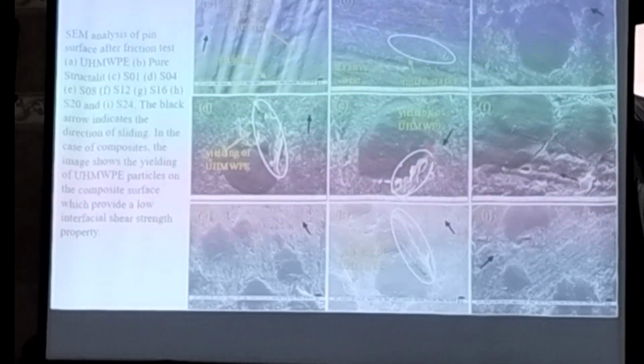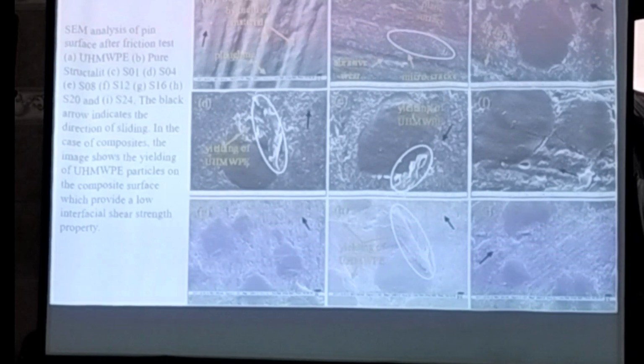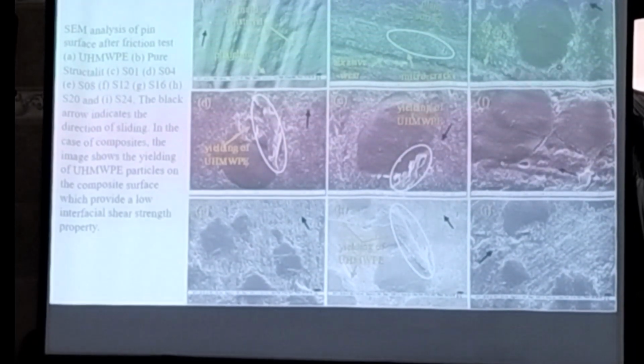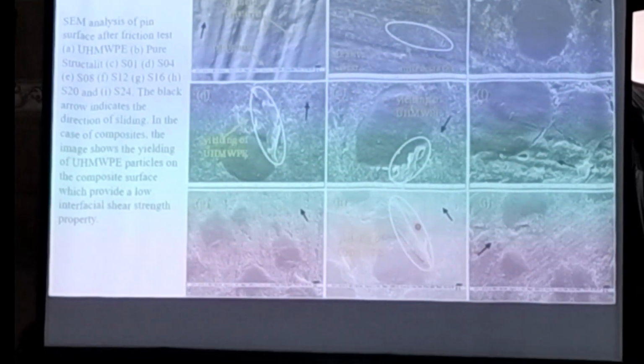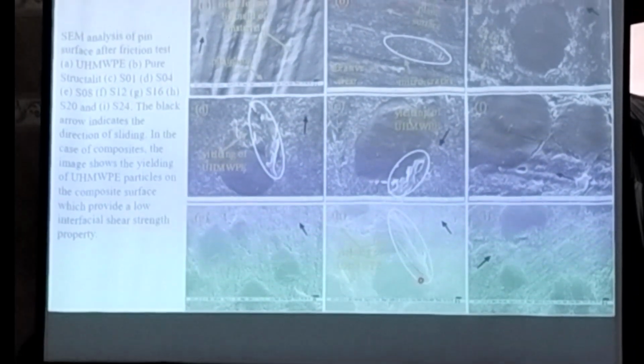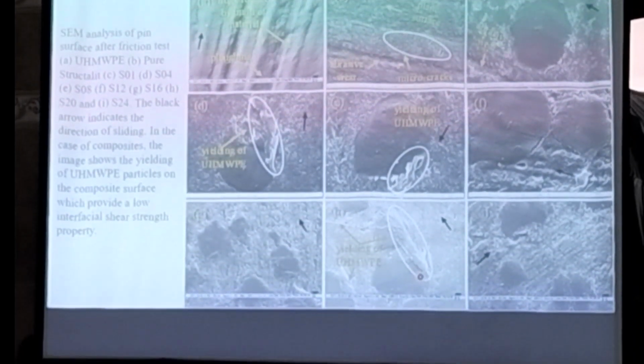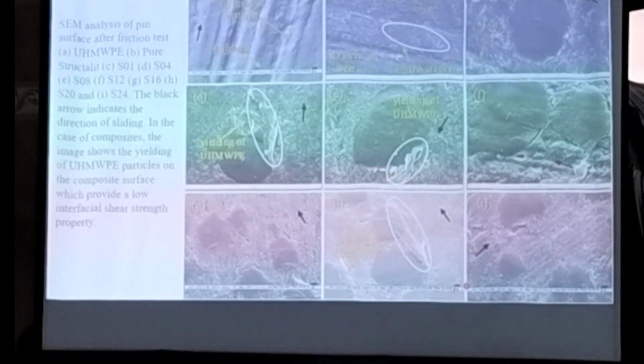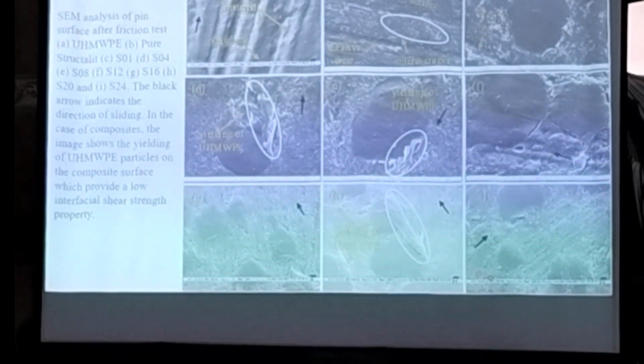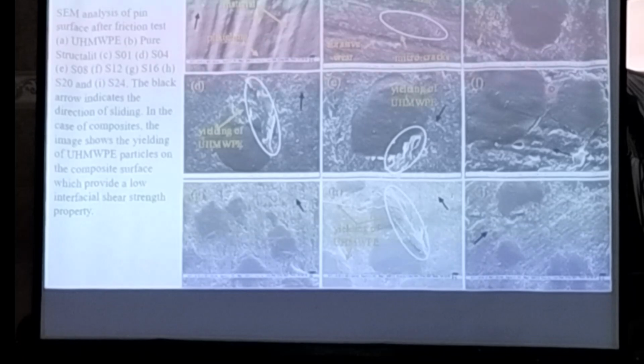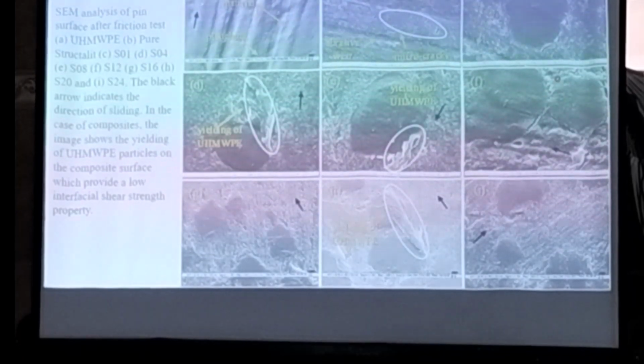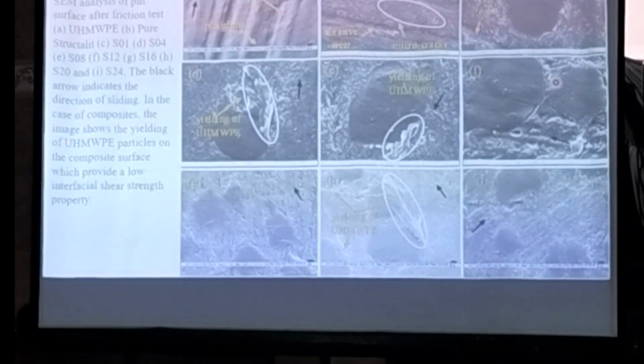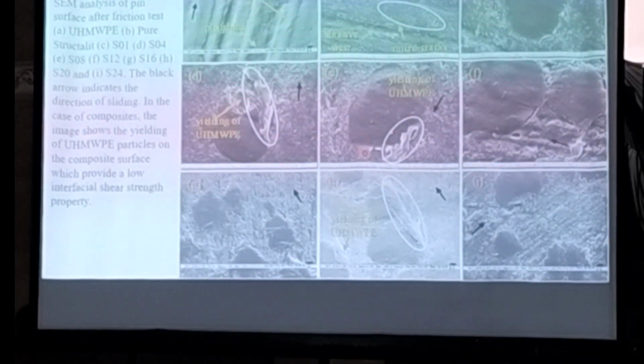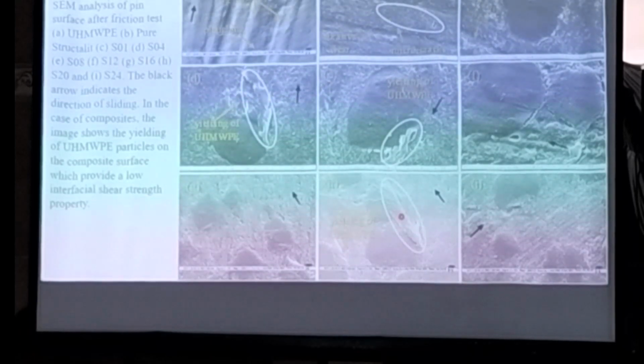And here you can see after the wear test how the surfaces look, and you can clearly see UHMWPE particles here, as well as some extension of UHMWPE molecules, which try to cover the surface and protect the surface. Okay? But in some cases, we do see some cracks here, crack development between the particle and the matrix, which could be the reason for wear, but in general we see that surfaces are very smooth and